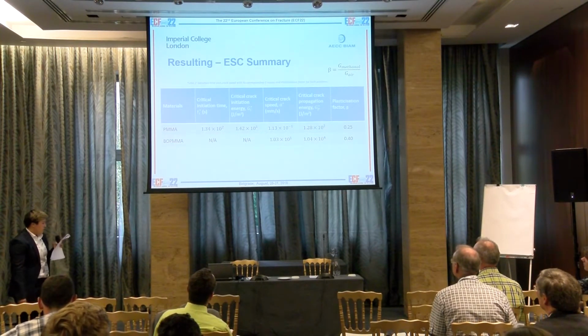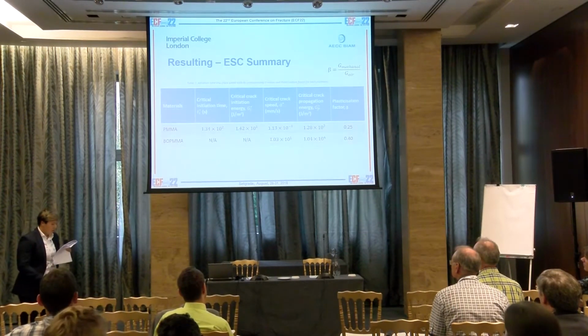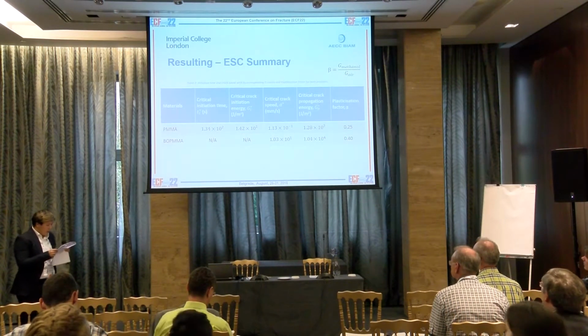So here is a summary table of the critical initiation time and crack speed with its corresponding G value. The results show that BOPMMA has a greater resistance to ESC than amorphous PMMA. This is probably due to the aligned polymer chains of BOPMMA having less free volume and hence a lower flow velocity within the polymer. Both critical crack speed and critical crack propagation energy have increased 2 orders of magnitude from its amorphous to biaxial orientated structure. And you can see from the plasticization factor, methanol has a greater impact on amorphous PMMA.